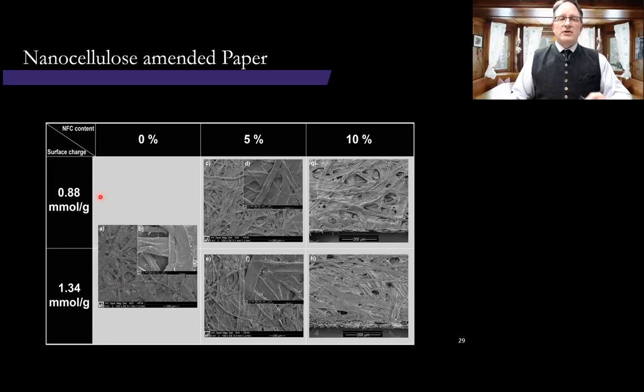Looking at the low charge reinforcement, as we increased the addition of NFC at 5%, we can detect a measurable densification of the sheet and a closing up of the pores in the sheet. That increased as we doubled the addition rate. And in this image, you can actually see the edge of the paper. And we confirmed this by measuring caliper of these sheets as well. Same trend with the higher charge at 5%. Not as much of a closing up of the sheet, but the same densification.